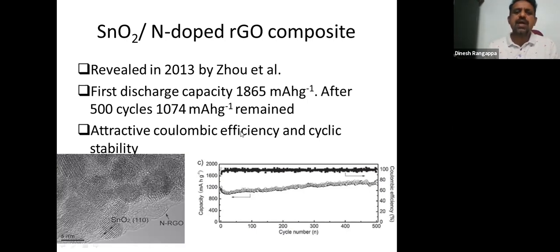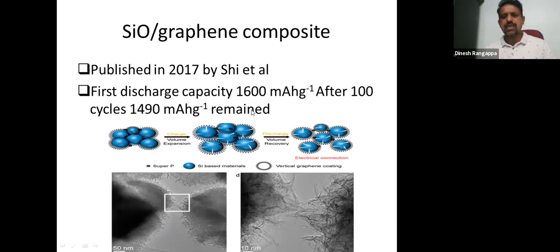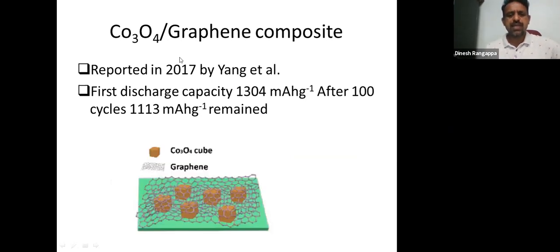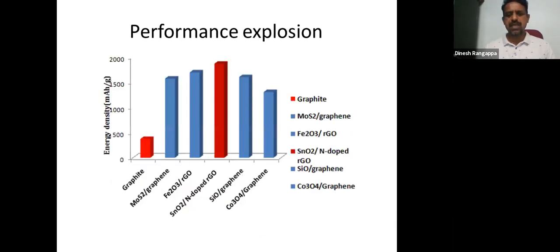So this type of metal oxide, metal sulfide RGO composite shows very good capacity, and this shows the progress in anode materials, especially when used with graphene-based nanocomposite for electrode material. This is another example of cobalt oxide graphene composite reported by Yang et al. So this shows there is a lot of progress with graphene-based nanocomposite for anode material with different metal oxides. Among all these, I think tin oxide, nitrogen-doped RGO composite shows a better, stable capacity